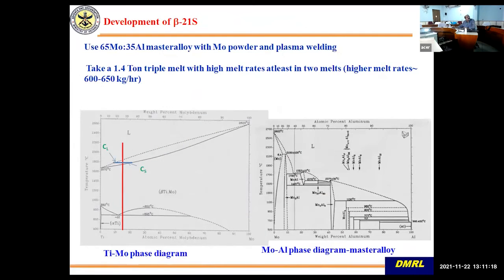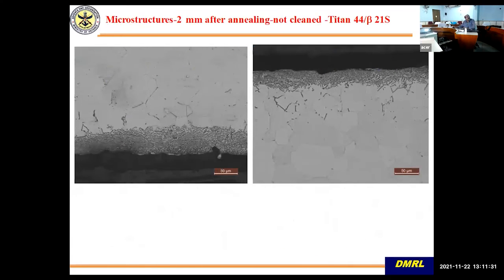Moly is not known to segregate because it has an isomorphous phase diagram. It is not like iron. So the problem here is the reverse of that of iron. So what we did is we changed the melting procedure. We melted at higher melt rate, and we changed to triple melting, so that our melt pool was there for longer time, and so that moly could dissolve.